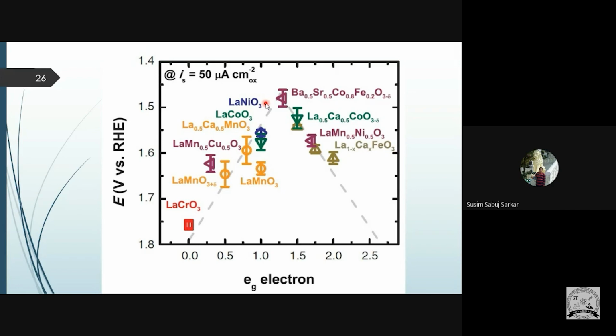But the main thing is that everything depends upon the M and O bond. That will determine, as I told, the bond between oxygen and the transition metal, which depends upon the Eg orbital or Eg filling of the transition metal. That will determine how effective it will be. I'm talking mainly about the activity of the transition metal catalyst, not the other things, the durability and the long term stability. That is another topic. Mainly I'm focusing on the activity here.